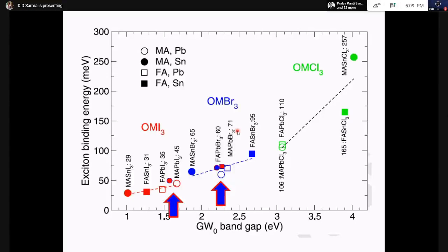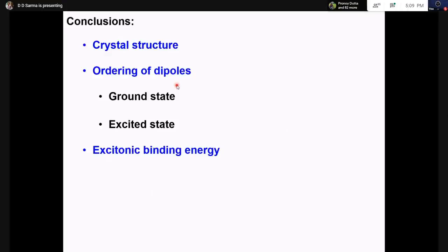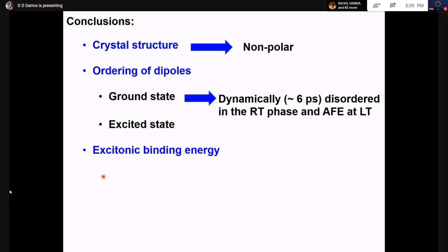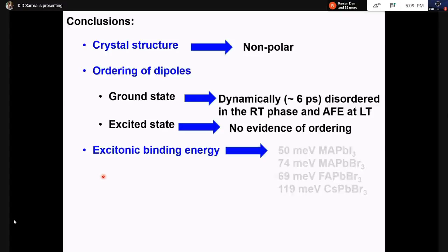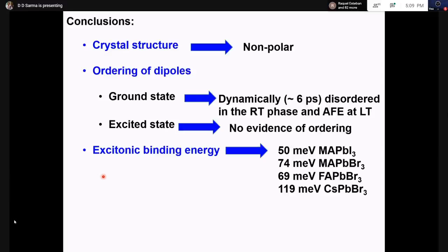Before I end, let me first summarize the conclusion, what I've shown today with a long introduction, why we are excited about it, and there are many more things that still continue to excite us. I said that there are open issues that we had addressed. Crystal structure, we conclude that it's non-polar. Ordering of the dipole, we said that it doesn't order at the room temperature phase. It's dynamically disordered, rotating with a time scale of about 6 picoseconds, and antiferroelectrically ordered largely at low temperature. Excited state also doesn't give rise to any ordering. And the excitonic binding energies, these are the materials that we have estimated, and these are the values.